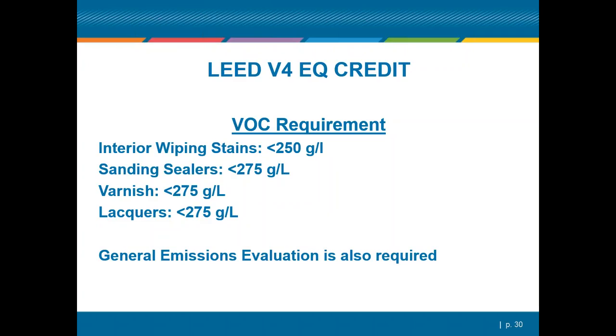But normally things of a solvent nature that have a high solvent capacity, and the 275, 250 ranges would be considered a higher capacity solvent product, normally will not pass. As a matter of fact, to a large extent we don't even put those in for small chamber testing because it's a waste of money to even test those, knowing what the VOC content is and knowing what kind of threshold we have to meet on the small chamber testing.